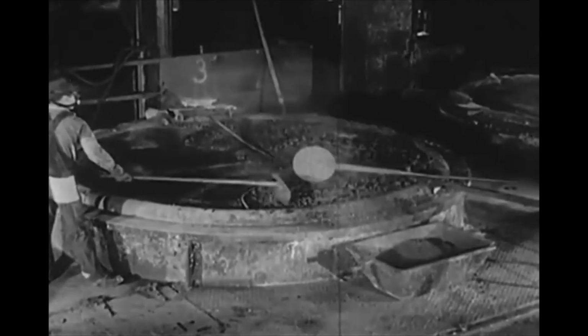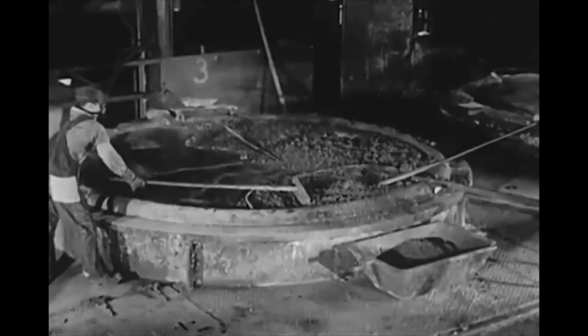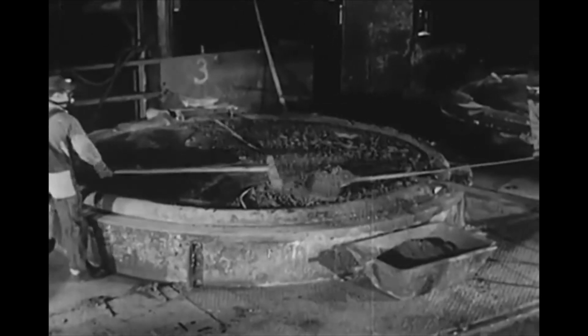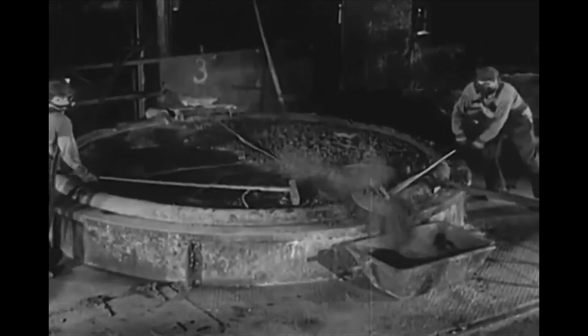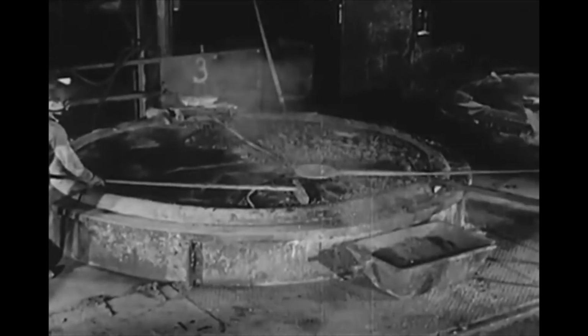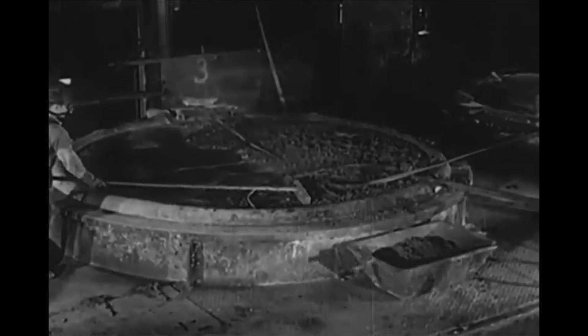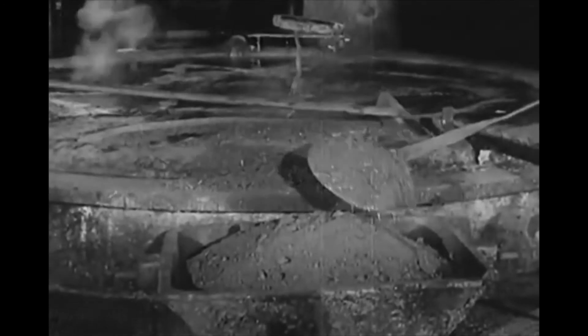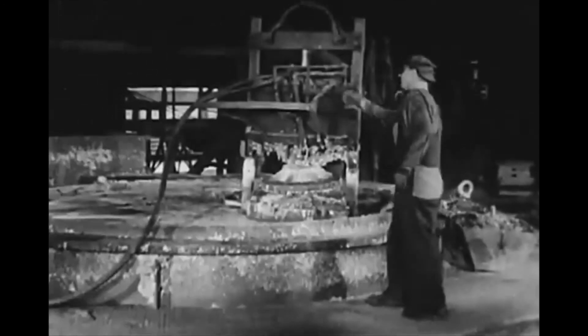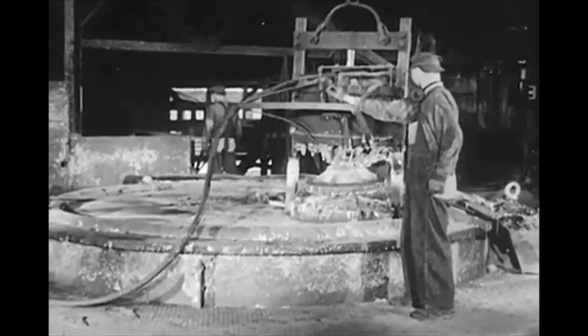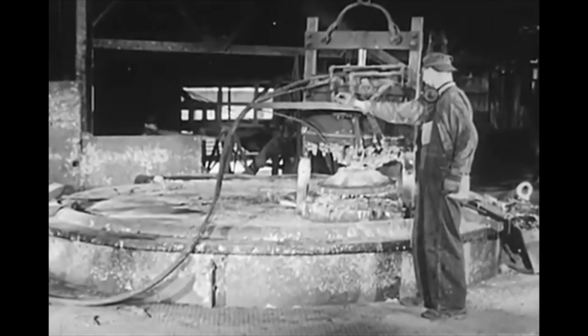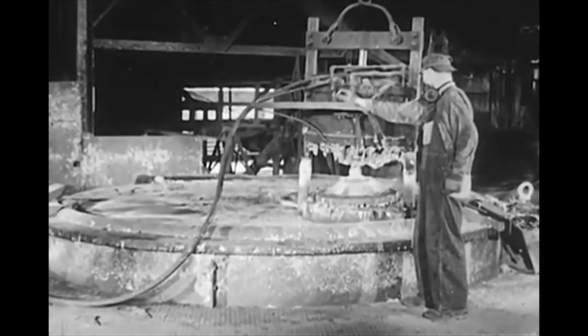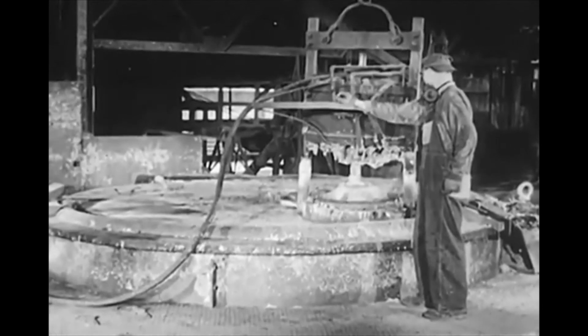Different types of lead are made according to the uses for which the metal is intended. Here, the remaining dross is removed, and the lead is allowed to cool to 625 degrees Fahrenheit. This is called chemical lead. Other types of lead are made where it's necessary to remove the silver to improve the purity of the lead. Zinc is added to the metallic lead in the refining process for the removal of silver. The zinc alloys with the silver, then floats to the top and is skimmed off.